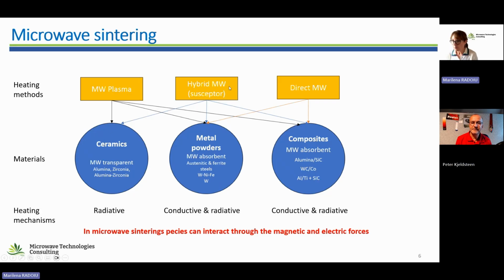Then direct microwave heating can be applied to composites and to microwave susceptors. And there is another method, which I call the hybrid microwave heating method. In the literature they call it infrared microwave, but basically they use a ceramic green compact, or this compact is made in a microwave susceptor, a material that absorbs microwaves very well and doesn't melt, like silicon carbide. Silicon carbide will get very hot, even red hot, and that will send infrared, so by radiation, into your ceramic or even metal. This is what the hybrid microwave is.